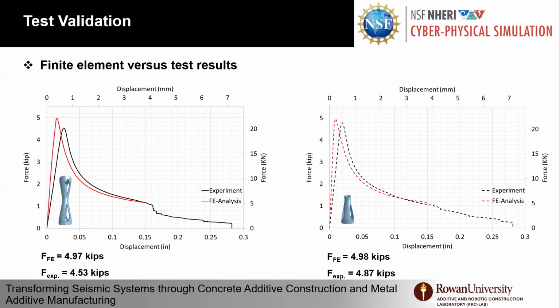But it seems you have to also get the mechanical properties. Is that elastic buckling when it fails, or is that inelastic buckling? This thing is almost bifurcation. It's inelastic. Yeah, because it's rounded. Okay. And not all of the legs, I'll just call them, buckle concurrently. For the double funnel, the lower side buckled without the top one. And the second specimen is only the top one tested.